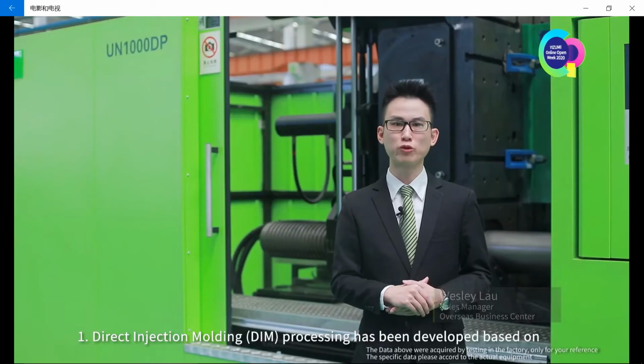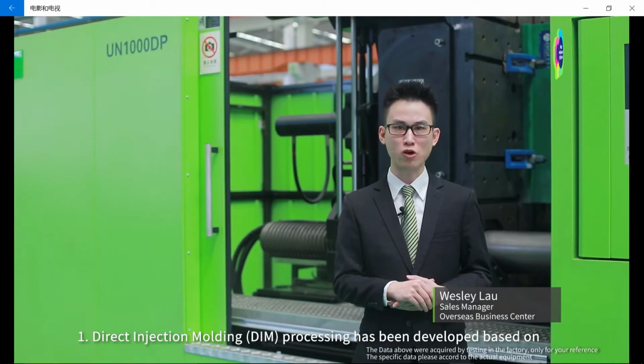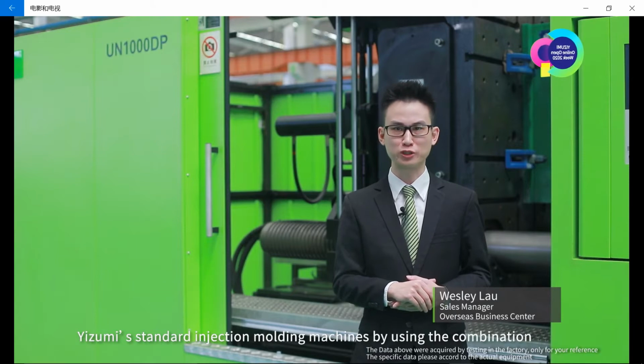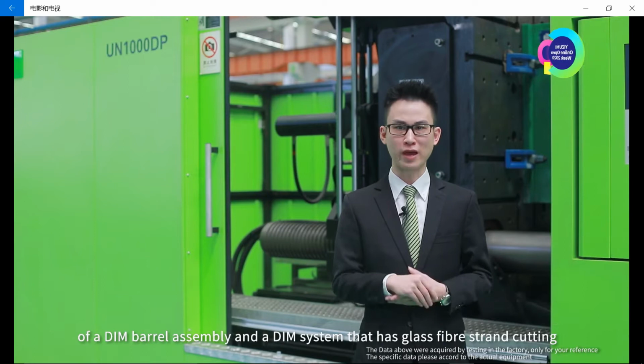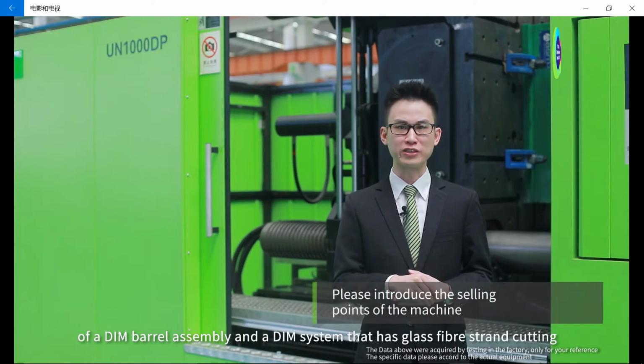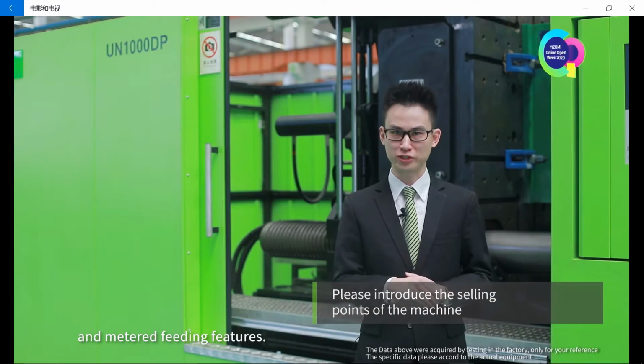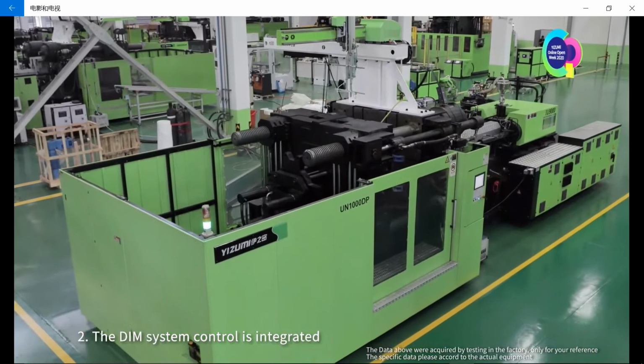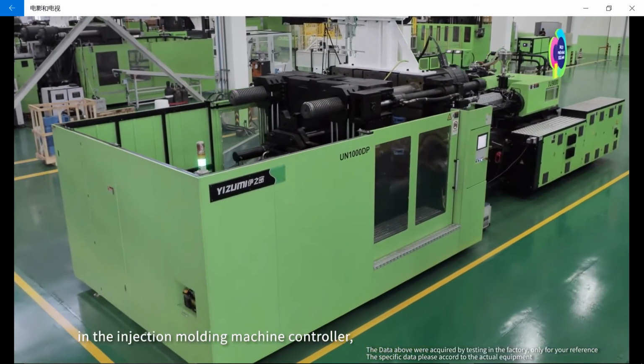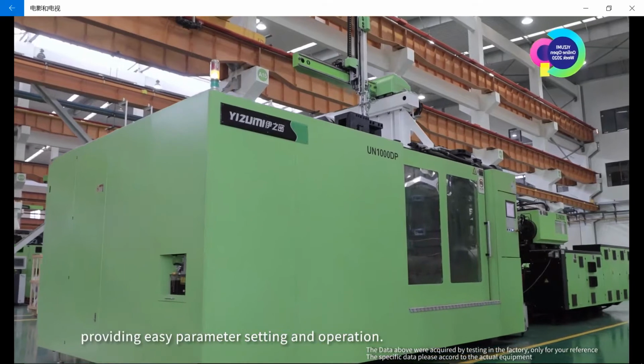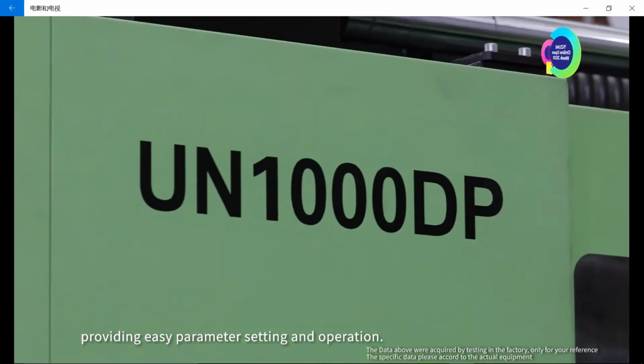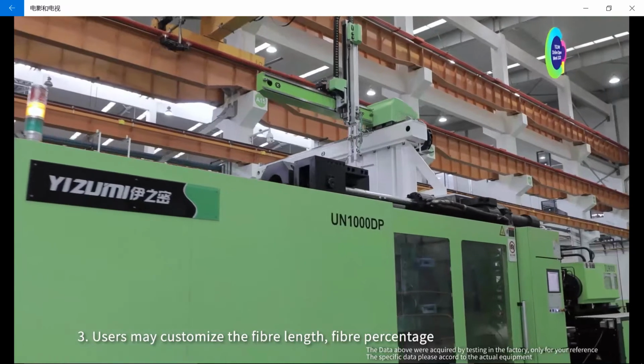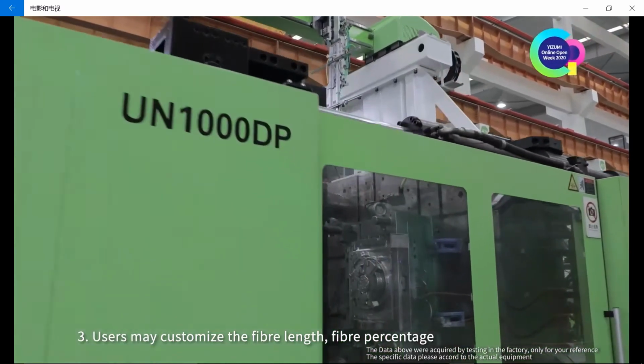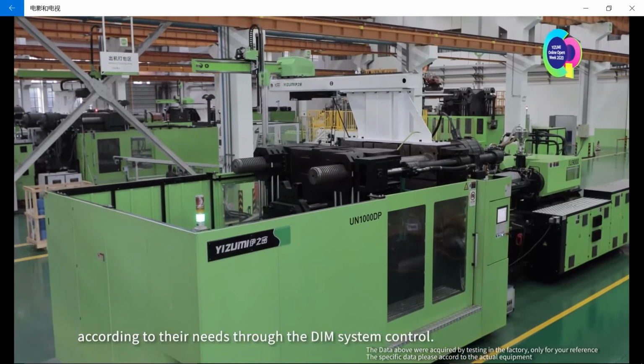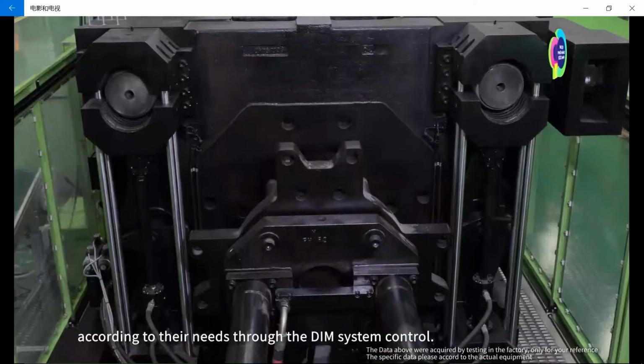Direct injection molding processing has been developed based on Yizumi's standard injection molding machines by using a combination of a DIM barrel assembly and a DIM system that has glass fiber strand cutting and metered feeding features. The DIM system control is integrated in the injection molding machine controller, providing easy parameter settings and operations. Users may customize the fiber length, fiber percentage, and material combinations according to their needs through the DIM system control.